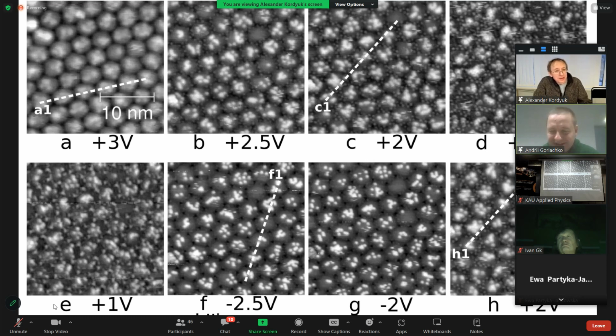So in this case, we just see through the graphene layer very nicely. All the other images are situations in between. Also, these are at positive volts, so these are the empty electronic states of the sample, that is, of the substrate and the graphene together. And for negative voltages, for example F and G, occupied states.